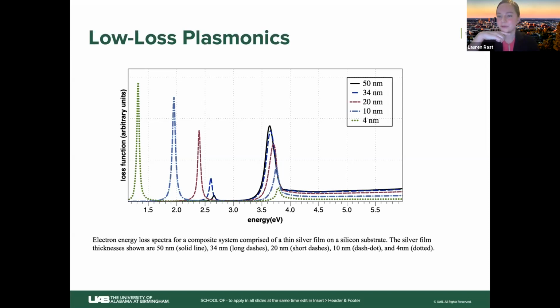So there are issues though. Fabrication of thin uniform metallic films can be really challenging. Thin metallic films tend to form small islands, and they often require an adhesion layer for the substrate, and these adhesion layers, as we said, these quasi particles interact strongly with one another, right? So what happens is it changes the optoelectronic properties of the system when you have these adhesion layers. And even really thin noble metal films have significant ohmic losses at visible wavelengths. So thin noble metallic layers might be advantageous for low loss plasmonics as part of some kind of a composite structure. Okay.